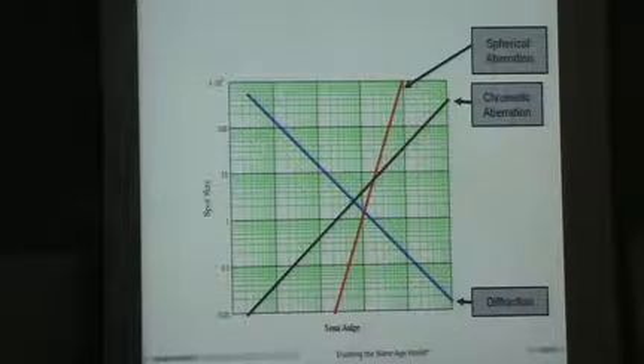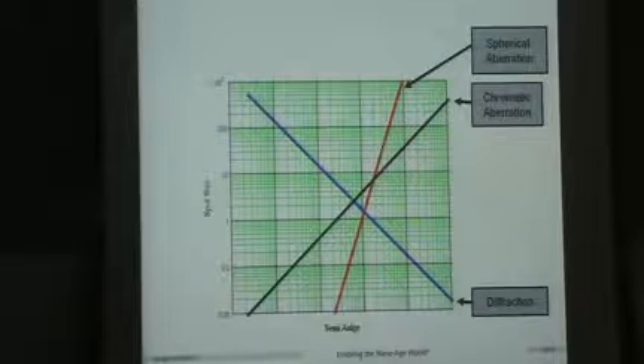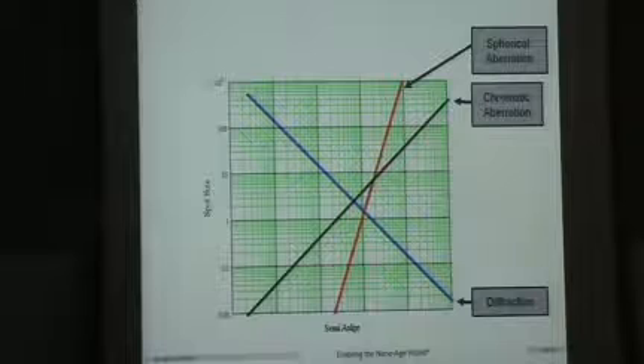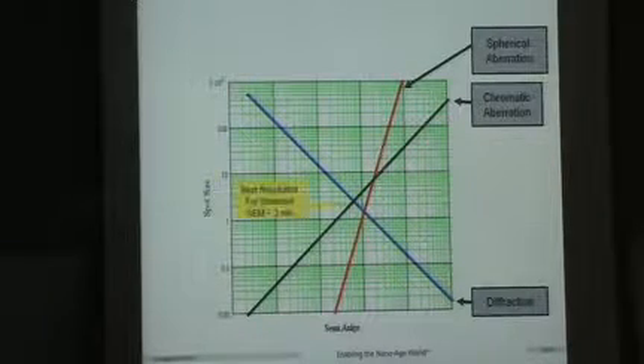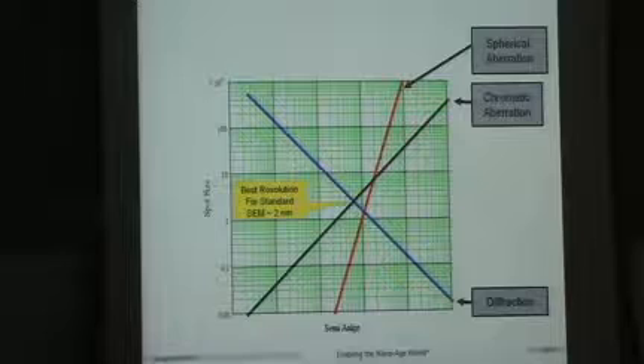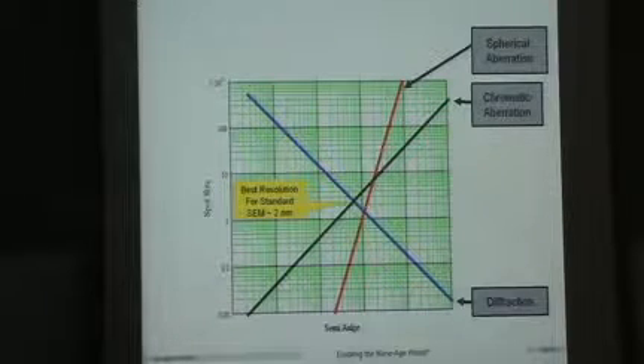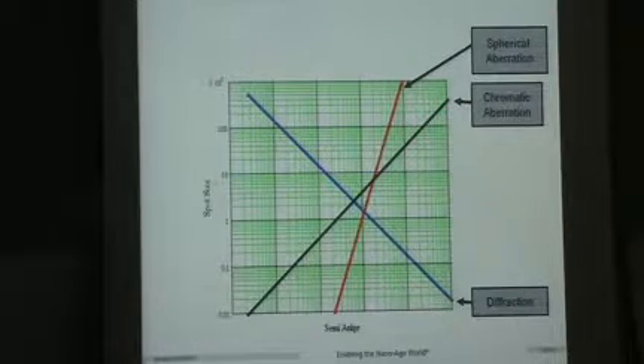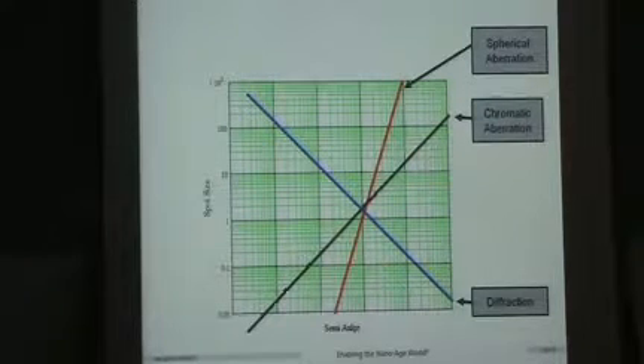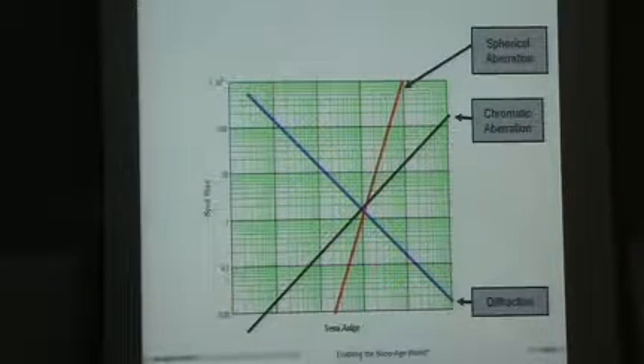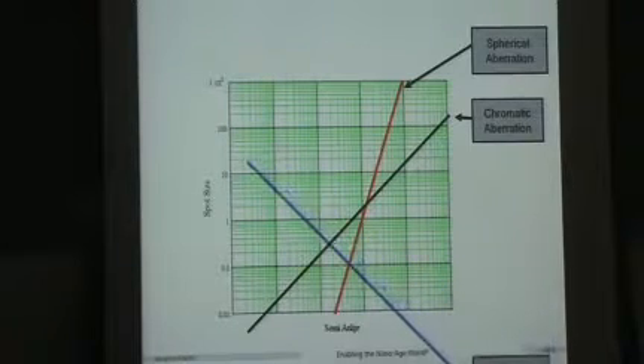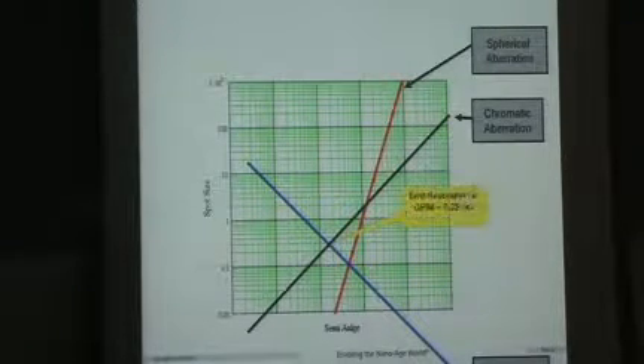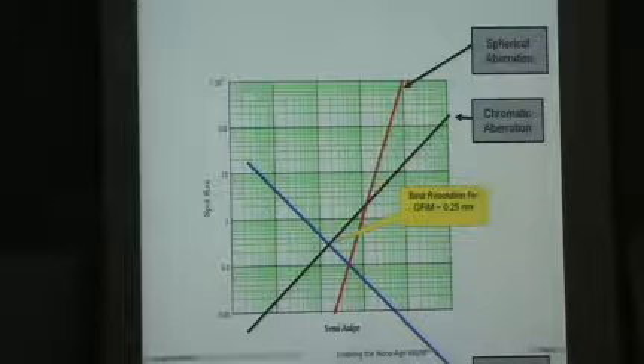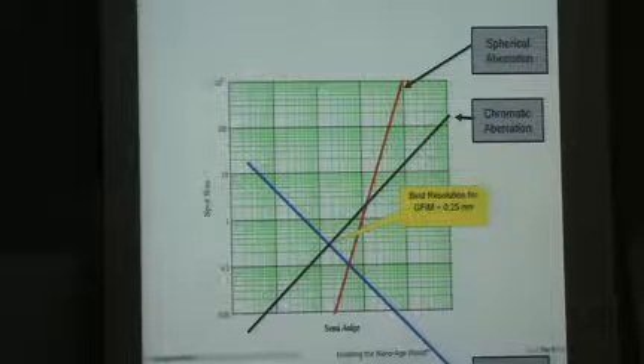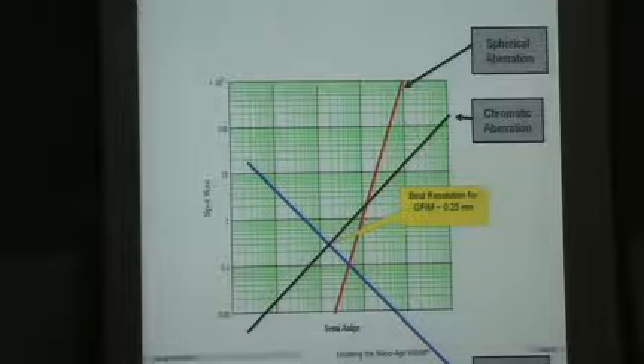And then ultimately you get limited by diffraction, at least on a SEM you do, because it's a low mass, it's wave-like. But if we could drop that blue line by going to something more massive, like helium, this is the SEM, typical garden variety SEM, optimized at a couple of nanometers. Some of the better SEMs do better. But as we can drop our chromatic aberration, because we've got a smaller delta E over E, and we can drop diffraction because we've got so much more mass, now our best operating point gives us around 1/4 nanometer. So we're right around the size of an atom. We're able to focus that down to the size of the ion source.